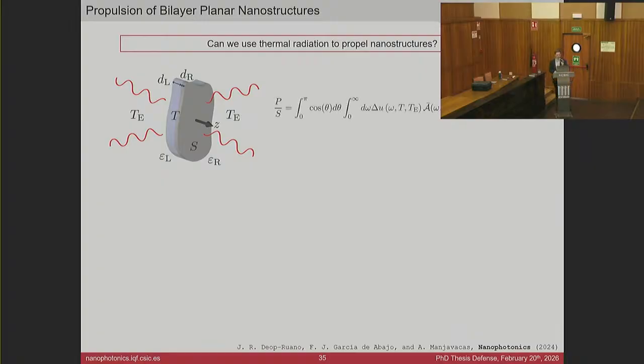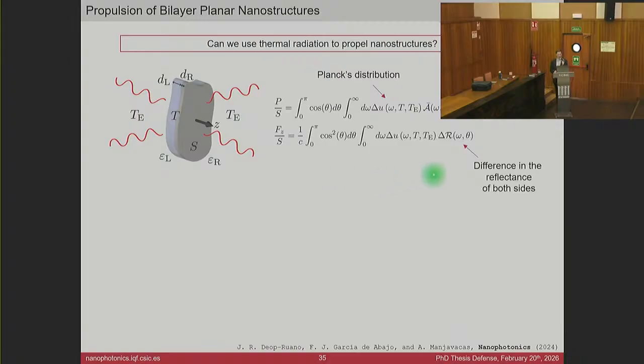I modeled this nanostructure by means of a gray body, in which we have the Planck's distribution, and we have to take into account the different emissivities of both layers. As I said, the interaction with the thermal radiation bath will give rise to a force that depends on the difference of the reflectance of both sides. We need different optical properties in the two layers.